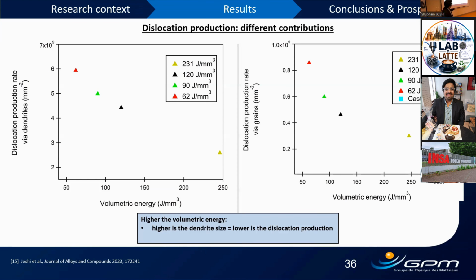If we look at the dislocation production rate via grains with respect to volumetric energy density, again we see the same trend. As we increase volumetric energy density, we see a decrement. And here we also have a reference, as-cast. For dendrites, we don't, because it's a recrystallized microstructure. So we can see that the cast contribution is the least. Despite having the same trend, what is also interesting is the absolute value given by the dendrites for every VED. If you compare with grains, it is 6 or 7 times higher for dendrites. So here is the first indication that dendrites seem to be the most influential for strain hardening.